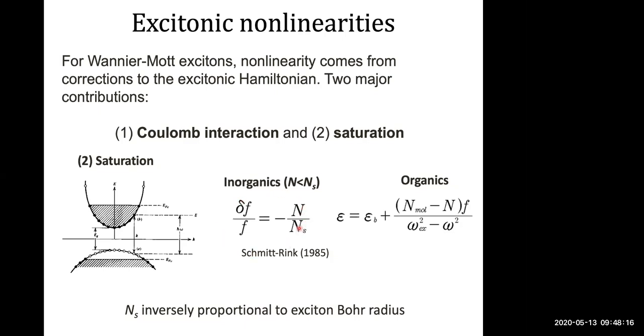So N is the exciton density, and S is what we would call the saturation density. This reduction in oscillator strength leads to a reduction in the Rabi splitting and an effective blue shift of the polariton resonance. We effectively have the same in organics, but in organics, this is coming from a reduction in the ground state occupancy, so a ground state bleach. And N molecules here would be the total number of molecules, N would be the number of excitations in the system. And given that the collective Rabi splitting scales as the square root of N, where N would normally be the ground state occupancy, which here has been relabeled N molecules minus N, as you increase the number of excitations, you reduce the Rabi splitting and you create a blue shift of the lower polariton branch.